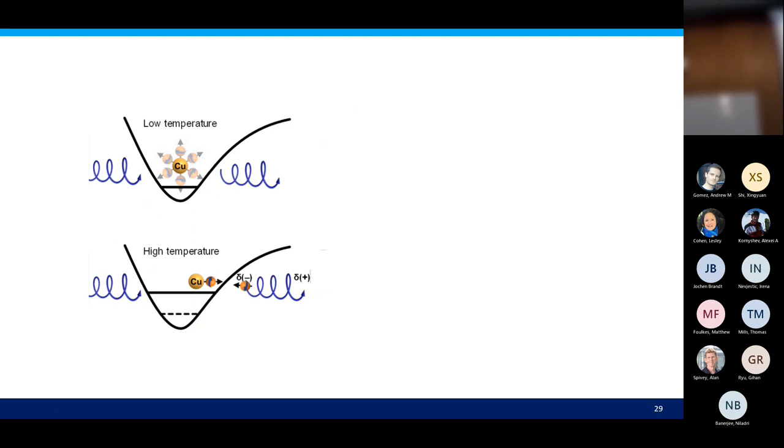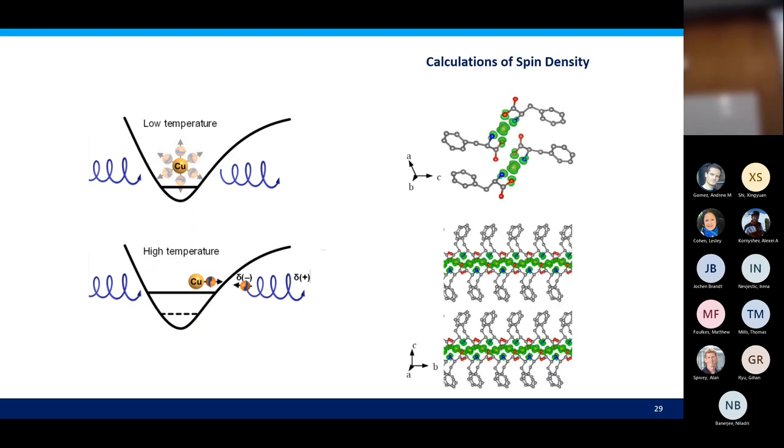So the copper plus now polarizes the more, with more charge polarization. The chiral molecules in the crystal, as I told you, when they are charge polarized, they are also spin polarized. So there is a spin-spin interaction between the copper and the crystal. When we calculate it, what you see is that the copper actually builds spin-oriented layers in the system at high temperature. So the motion of the copper within its cage, because of the anisotropy of the g factor of the copper, creates the magnetization.